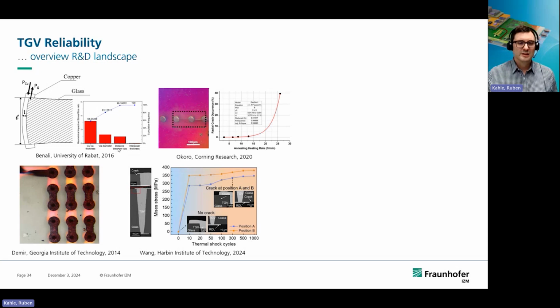For example, it's important with copper that after plating, you will need to have an annealing. Of course, it's important to not do this too fast. This has been shown by Okoro and Corning Research in 2020. And similar to this are thermal shock cycles from Wang in 2024. This is quite new. Both of these indicate in the same direction. Copper is creeping at some point, and copper could do some crazy stuff. It is not only elastic, it will also get into plastic deformation. And you should better not allow copper to do this, because then you're creating some really awful defects. But this has been learned, and we can come along with this.